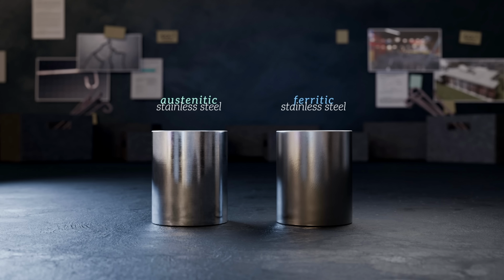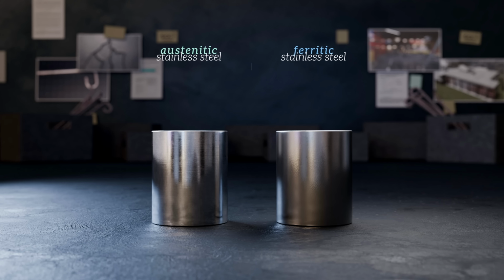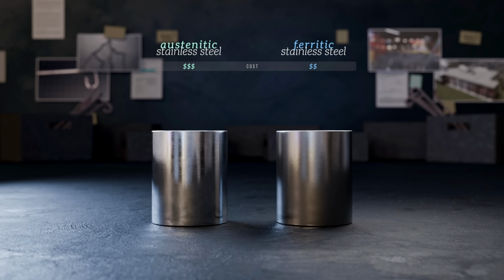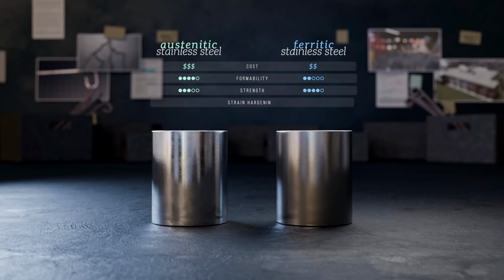Because they don't contain nickel, ferritic stainless steels tend to be much less expensive, but they're harder to work with. Austenitic grades are far more ductile and easier to form into complex shapes. Ferritic stainless steels tend to have slightly higher yield strength in the as-supplied condition, but austenitics harden when deformed and can reach much higher strengths than ferritics after cold working. And when it comes to general corrosion resistance, austenitic grades tend to outperform lower chromium ferritic grades, although higher chromium grades can achieve comparable performance.